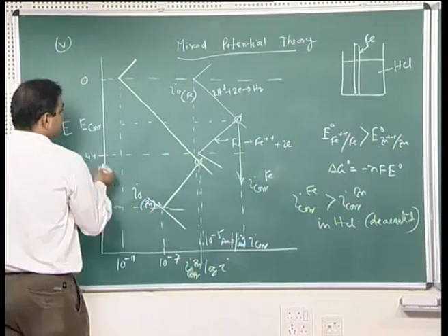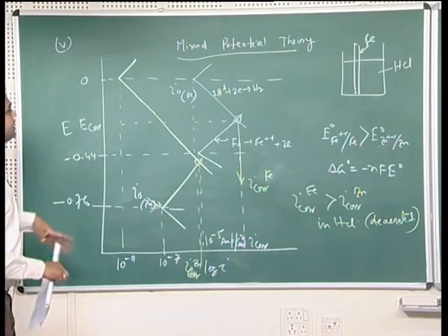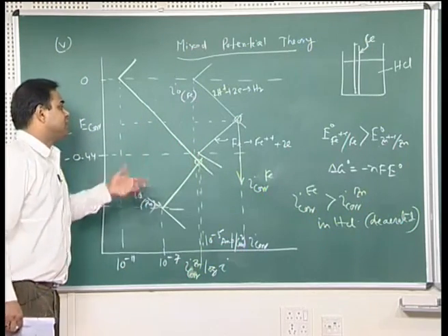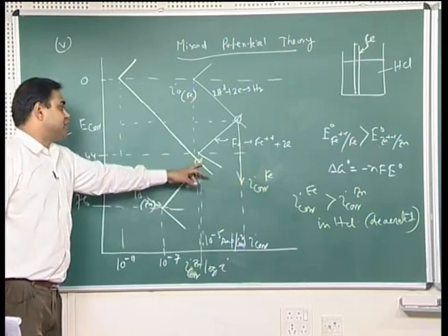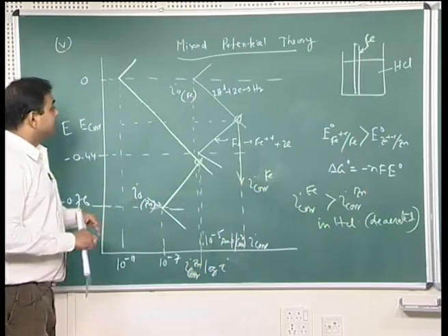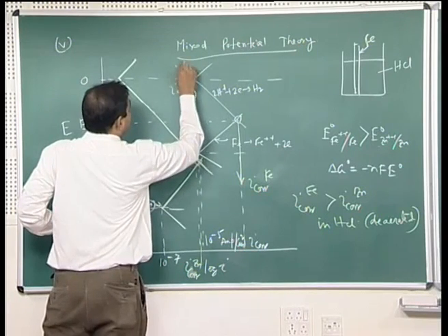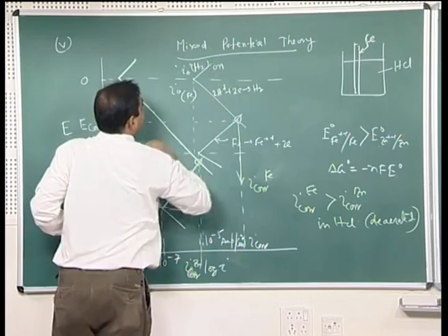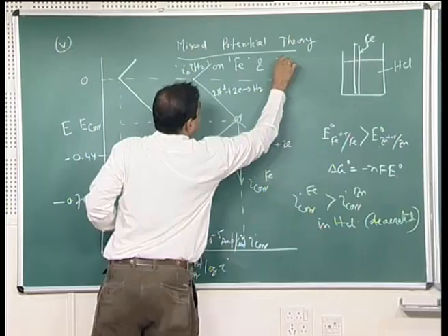There is one more important governing factor which decides which one would corrode at a higher rate than the other one. For example, iron here is corroding at a higher rate than zinc, even if iron has higher reduction potential compared to zinc. One of the main guiding factors is I0 of hydrogen evolution reaction on iron surface as well as zinc surface.